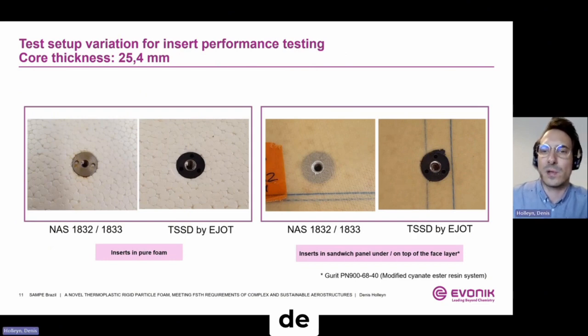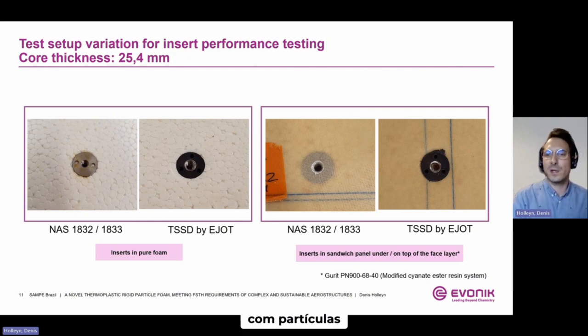In our case study around the topic of insert integration, we analyzed four different cases of how to put those inserts into a foam panel. We differentiate between inserts integrated into the pure foam and inserts integrated into sandwich panels. All metallic inserts have been included into the foaming mold before filling it with particles, and the thermoplastic inserts have been introduced after the foaming process or even after the lamination of the foam part. On the next slide, we will have a look at the mechanical performance of all these combinations when it comes to their specific pull-out forces.